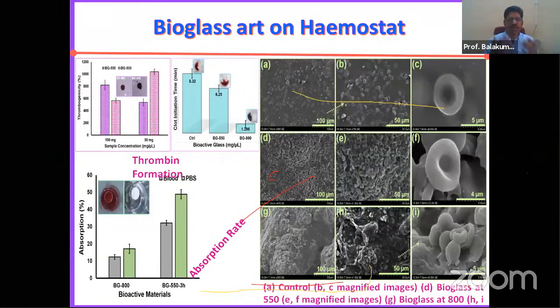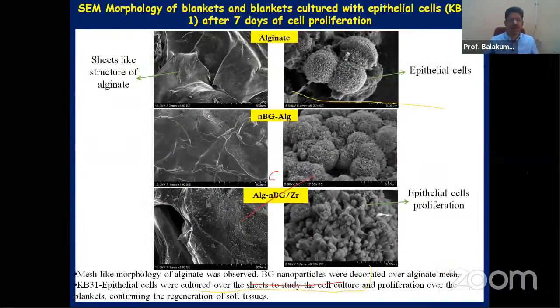Similarly, we also developed a bioglass material to arrest blood. Here we have the hemostat data, that is, thrombogenicity and absorption. We have shown that and systematically evaluated it. You can see that when the material is prepared at 800 degrees temperature, the hemostat properties are very good, and it immediately arrests the bleeding. So this is one of the materials that we have developed.